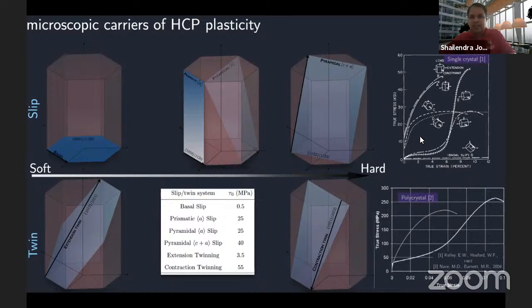So what that does, as I mentioned earlier, is that it creates a remarkable landscape of anisotropic responses and tension-compression asymmetry, not only at the single crystal level, as shown in the top picture of the stress-strain curve, but also at the polycrystalline level, where the polycrystal response is now modulated or mediated by the textural effects. So the coupling between crystallography and texture plays out in the response of the polycrystal. But you can see some very similar qualitative behaviors between single crystals and polycrystals in that sense.